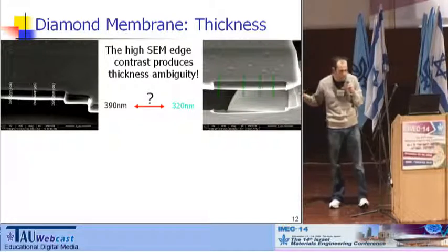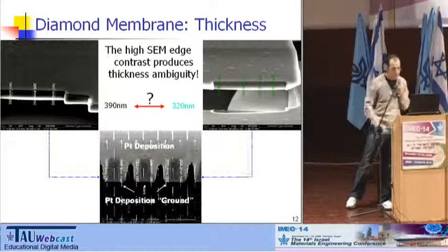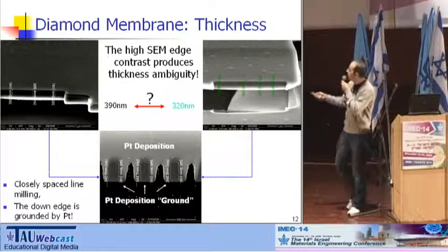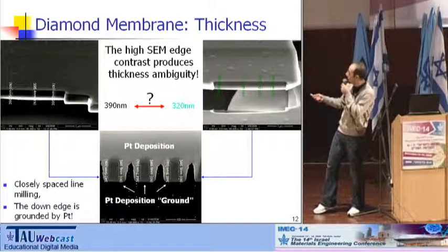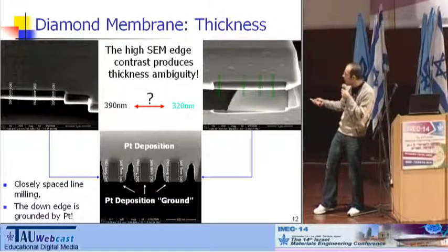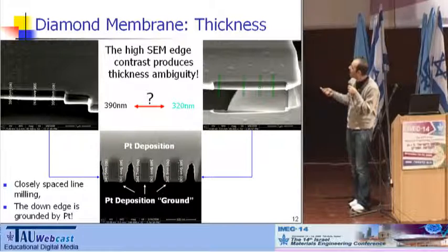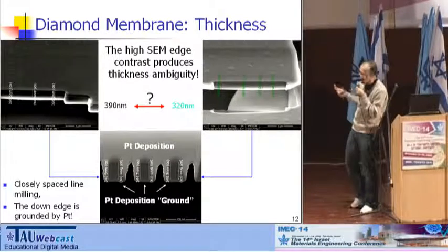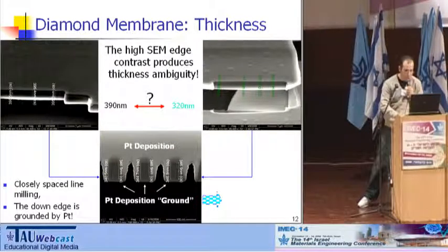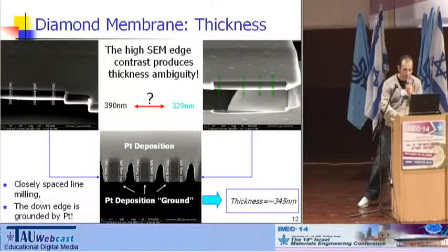for a precise optical device. So to tackle this problem, we have milled trenches in the diamond and deposited platinum, which actually grounded both the upper and the lower edges. In this way, you can see a very uniform measurement of the thickness, which turned out to be 345 nanometer.